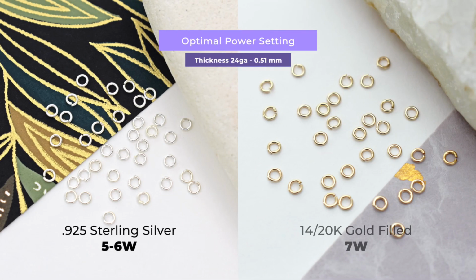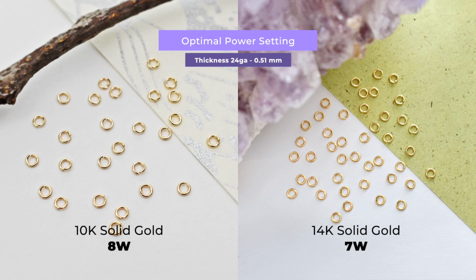For 24 gauge, silver is at 5 watts, gold filled at 7, 14 karat gold at 7 watts also. It was hard to be very specific because the difference for both 7 and 8 watts was very similar. And then at 10 karat gold, the best is at 8 watts.